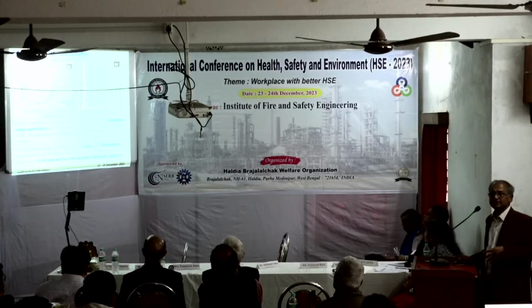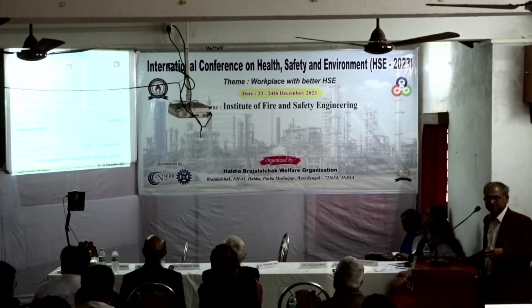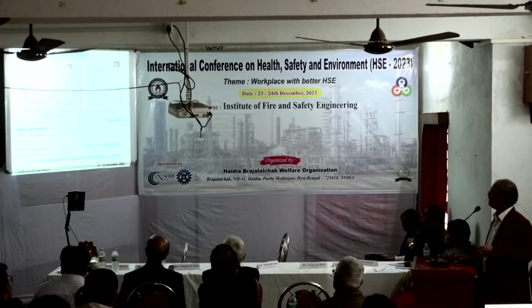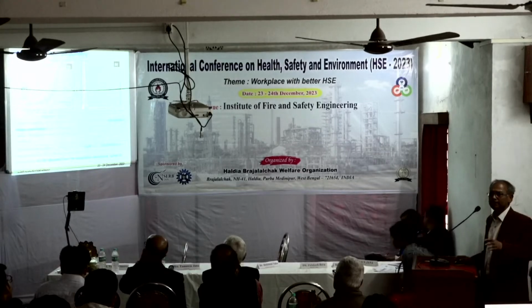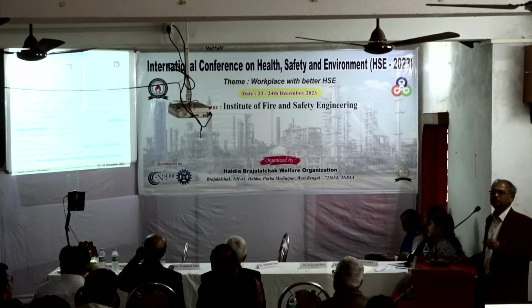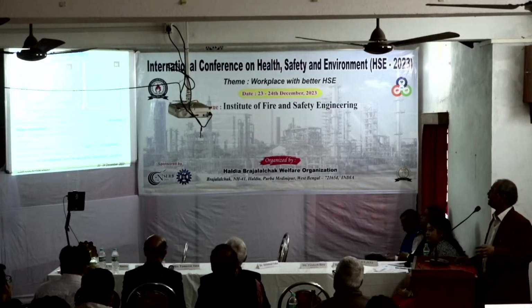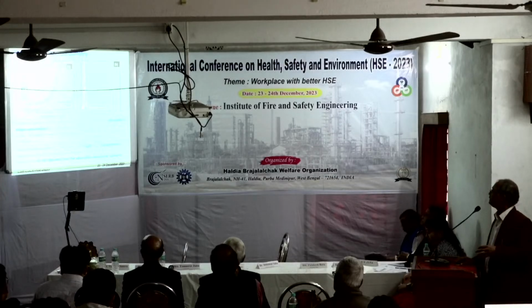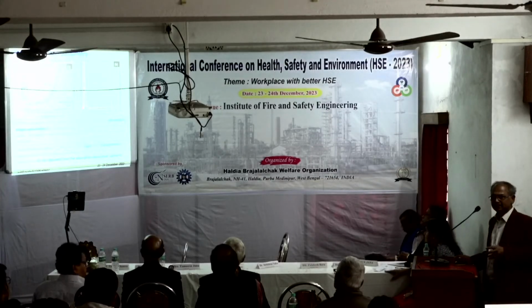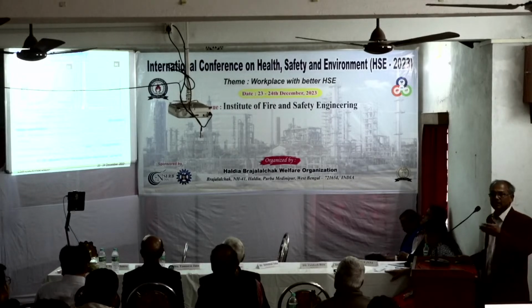We measured it by spectro ellipsometry method in our institute. It is a high value equipment where the thin film porosity can be accurately measured, and we obtained the porosity value 43.6%. That means this is the adsorption desorption curve which is popularly seen, which is always seen in our BET isotherm, but it is not BET isotherm.